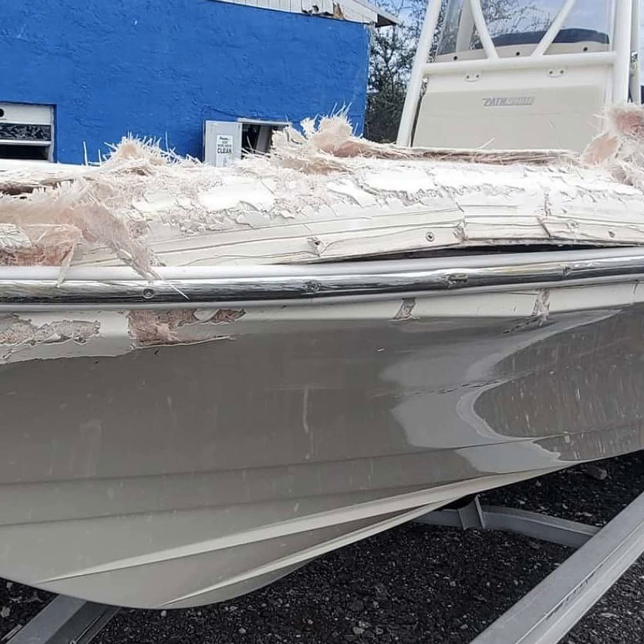Chop strand mat is a bunch of random fibers that are held together by a binder, and that binder breaks down with the styrene that's in the poly or the vinyl ester resin. So essentially, 60 seconds after you wet that chop strand mat out with resin, and this does not count for epoxy, this is only for resin that has styrene in it, the binder that holds all those individual fibers together is going to dissolve, and those fibers are going to become independent from one another. And when you roll over it with a bubble buster, you can really get it to go where you want it to go.